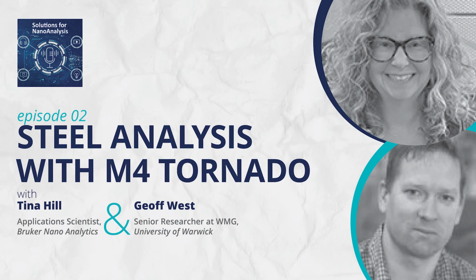And we do a lot of work with Tata Steel, which is one of the biggest suppliers in Europe for steels. And they're co-located here at Warwick with us. And they ask us, look, we want you to show the grain structure on this massive, great 5 kilogram steel block. And we want to know the segregation in there as well. And we've tried etching it, but how do you etch a 5 kilogram block and then image it? How do you do that? It's so much easier just to stick it on the XRF and do a map.